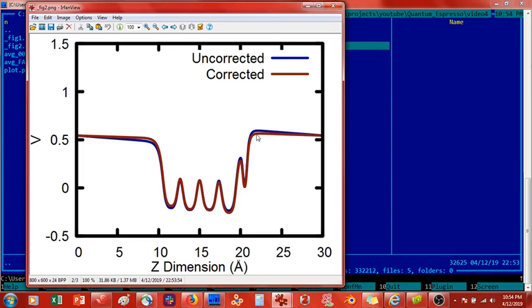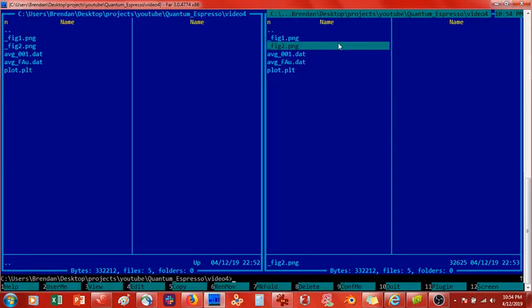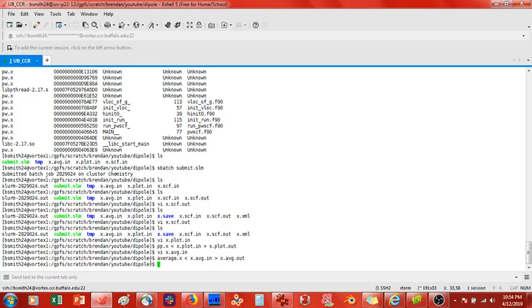The problem is that it still has a little bit of slope to it. And what I think, why I think this is happening is because we didn't exactly cancel out the dipole that was induced through addition of the fluorine atom. And so what that means is that we need to add more slope to our sawtooth potential. Basically, we need to find the slope that will actually cancel out this induced dipole. So let's go back to our program.